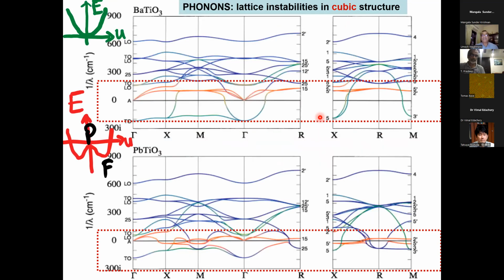So using first principles density functional theory, we determine what is called phonon dispersion. This is phonon frequency as a function of wave vector in the Brillouin zone of the cubic structure. You see the cubic structure is unstable at 0 temperature. So naturally what we see here, these are negative phonon frequencies, but they are actually imaginary phonon frequencies. And these are the unstable phonons that I introduced to you initially. Okay, so first principles calculations give us very precise access to all the lattice instabilities of a crystal.